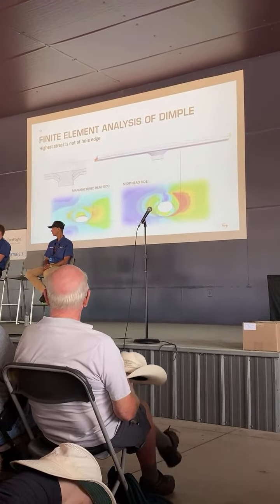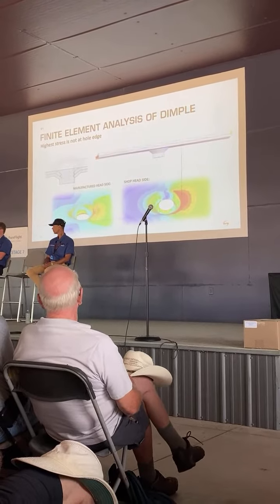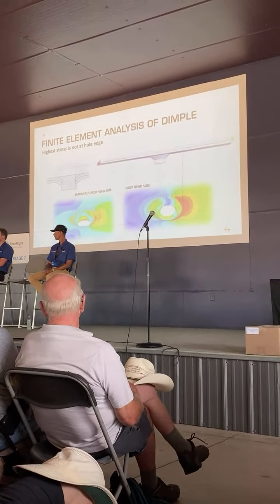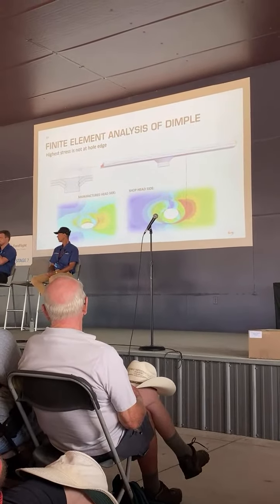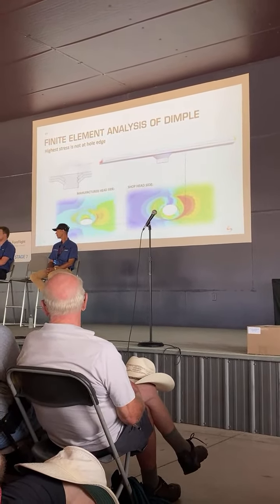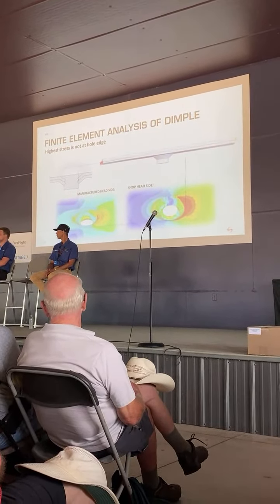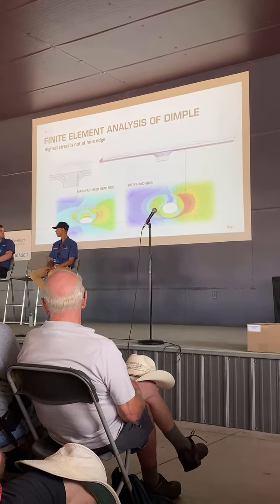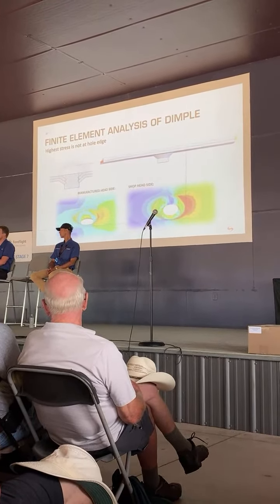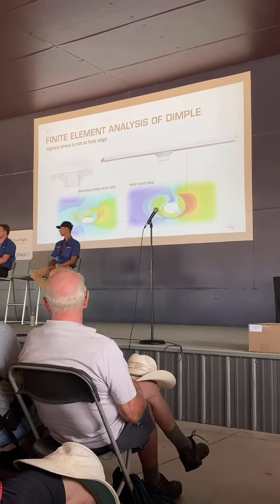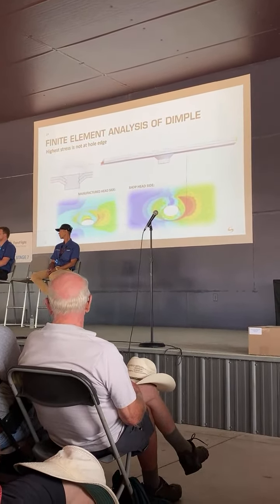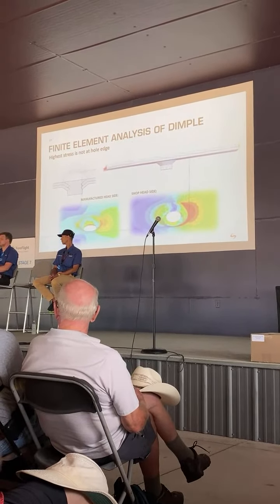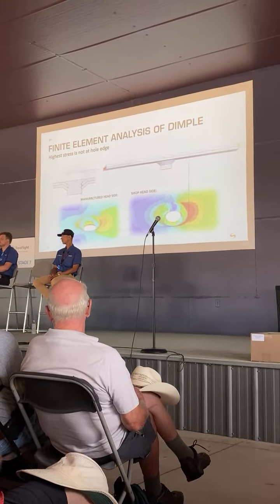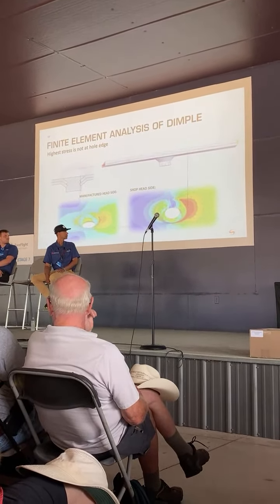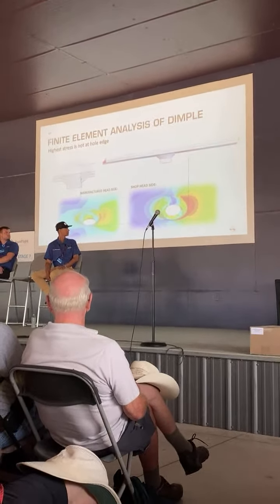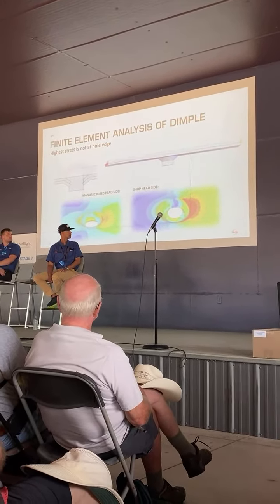Here's the finite element analysis model of the hole. And you can see from the top here the stress, I'm going to call this the 12 and 6 o'clock positions. The stress is being applied at the 12 and 6 o'clock positions here. You can see at the 3 and the 9 o'clock positions, there's a stress riser on the inside of the hole edge. We've taken the features, let's call them, or the cracks that are from the overload cracking, and oriented them at the 3 and the 9 position. We're currently orienting, as you can see here on the right side, we also have a high stress area in the rim of the dimple, which is where the crack is going to.